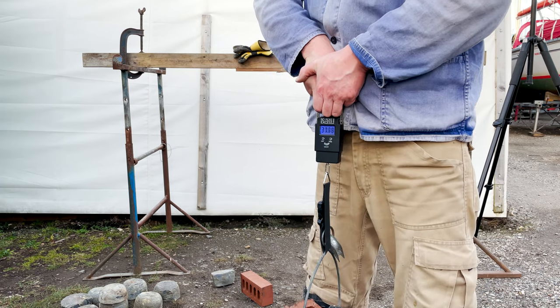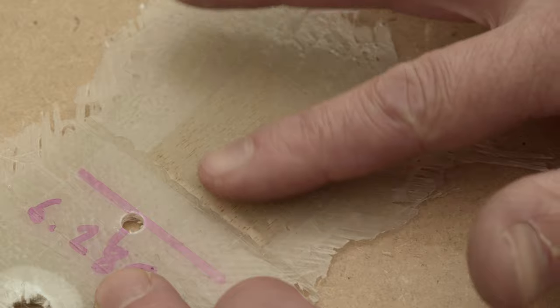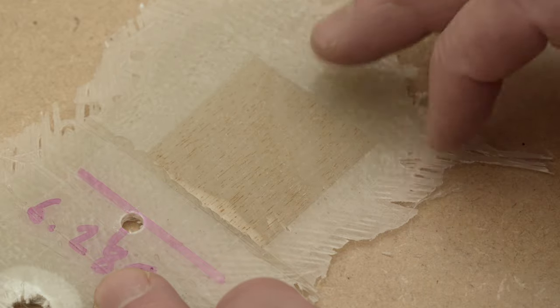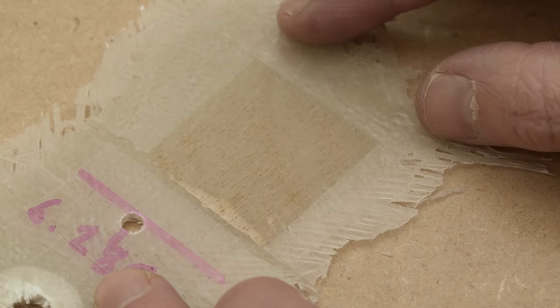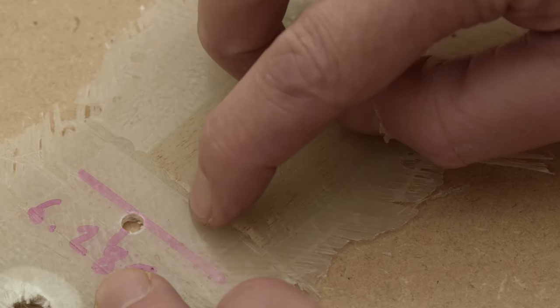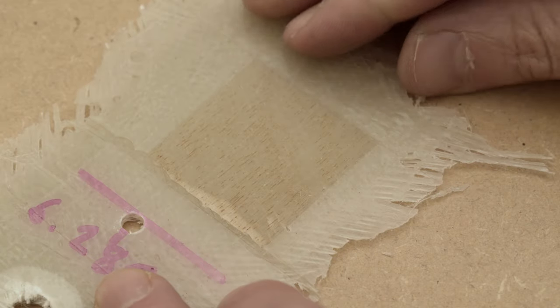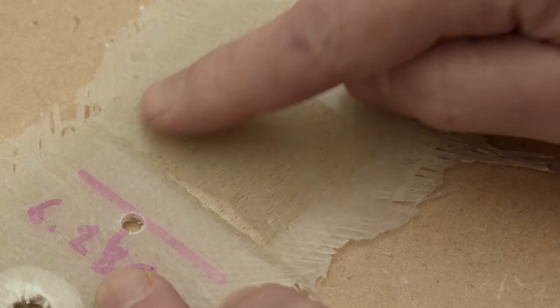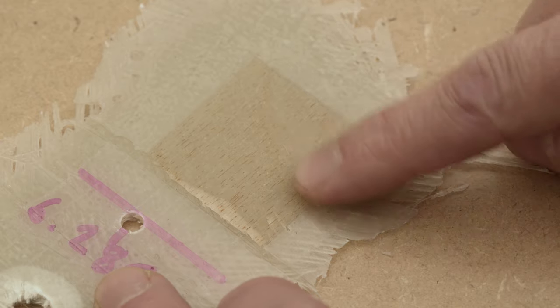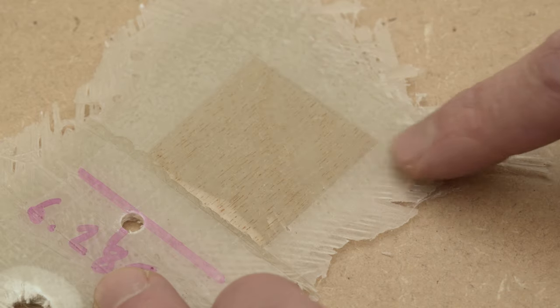So this is a close-up of the polyester tab, and even though I applied several coats of polyester resin before laying up any glass, it really looks as though that hasn't penetrated very deeply into the plywood at all, and only the smallest fibres of wood have been carried away.